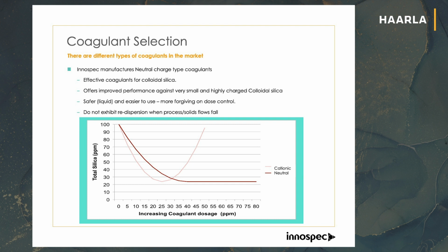With the cationic, what happens is the cationic covers it so far, which is up to here, where you get the minima. But if you keep on adding the cationic, it stays on the surface of the silica particle. So instead of having that negative charge keeping the particles apart, repelling, you've got a positive charge which is keeping them apart. So it's a different process that's forcing the silica particles apart, but it's detrimental to the process that you're wanting to do. So it's important when you're doing these to identify how you want to do it and optimize the dosage level, so that you're making sure you're getting optimum performance.